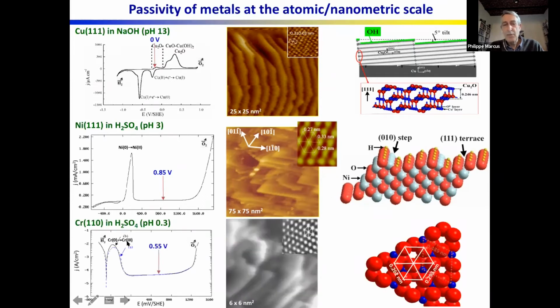And finally, the third pure metal that we looked at, chromium, shows similar trends, crystallinity, so highly ordered layer. And from this atomically resolved image, we can derive the structure, which is the structure of alpha Cr2O3, which is the basal plane. So that's the most stable surface that is formed on chromium.